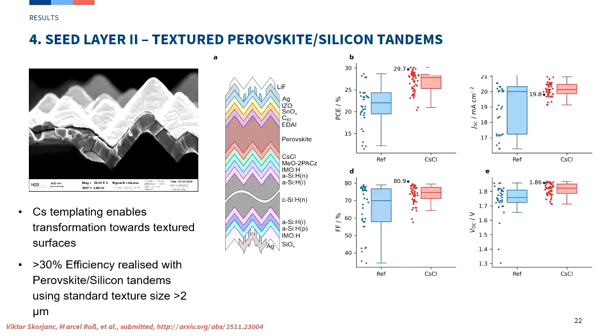And then, of course, we can implement that into tandem solar cells. Here this is a fully textured, conformally grown tandem solar cell. You see an SEM cross-section image here—this is the perovskite layer, fully conformally grown on the pyramids.